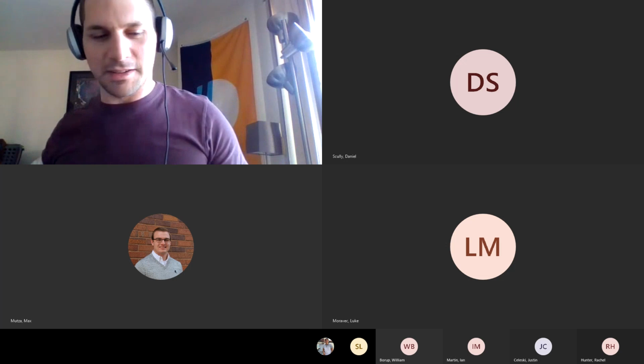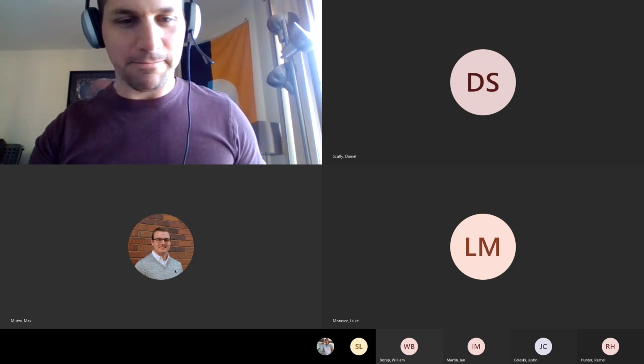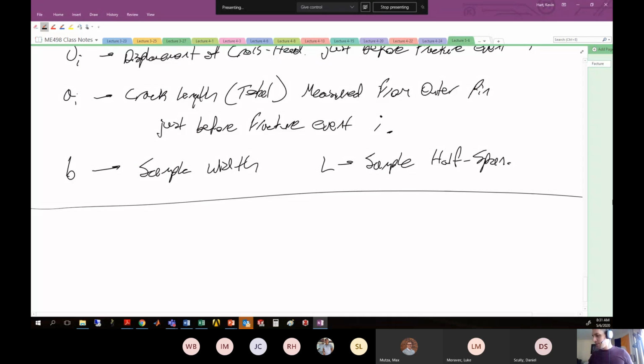Now, fantastic. Great. Marvelous. Let's get back to the writing pad. We've talked about analysis methods for mode 1 and mode 2 fracture of composites. And we generally understand that the matrix materials that make up composites are very brittle, and composites will generally fail in fracture before they fail in any of these other modes associated with strength metrics. The fibers inside of the composites are not really going to be the ones that fail most often. Usually it will be the brittle matrix phase that tends to fail because there's an initiated crack or a void inside your material where a fracture can initiate from.